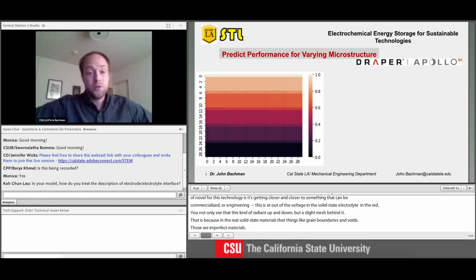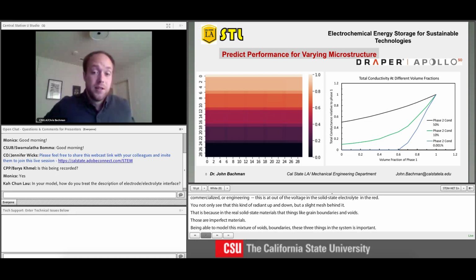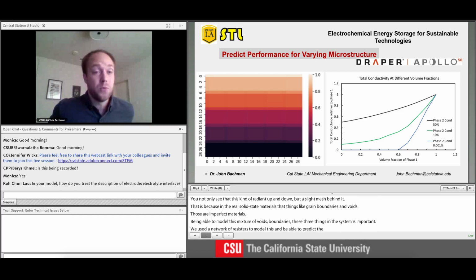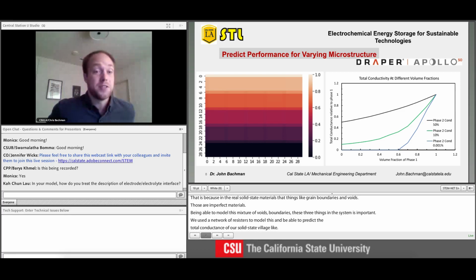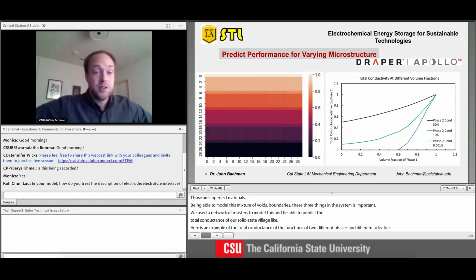And so we use a network of resistors to model this and be able to predict the total conductance of our solid state electrolytes. So here's an example of the total conductance as a function of two different phases when the phases have different conductivities. So you can then begin to see, all right, when the experimentalists make this solid state electrolyte,